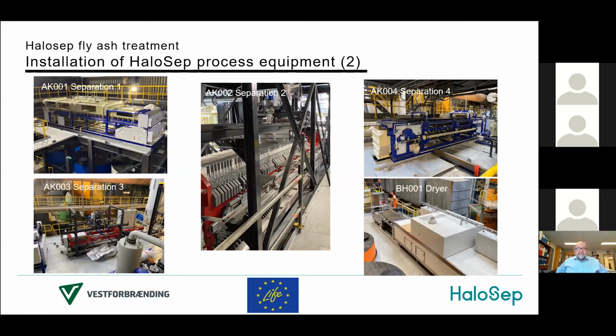The separation of different streams is done with classical chemical equipment. We have a separation stage 1, which is shown on the upper left. It's a band filter. In the middle, we have a filter press for the final dewatering of the washed treated fly ash. On the bottom left, we have the separation 3 for the separation of salt from precipitated metals. The upper right is the separation of washed metal product, and the filter cake from this is going into the dryer shown in the right bottom picture. Next, please.